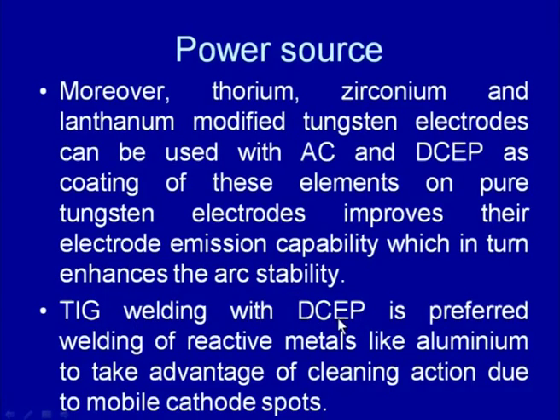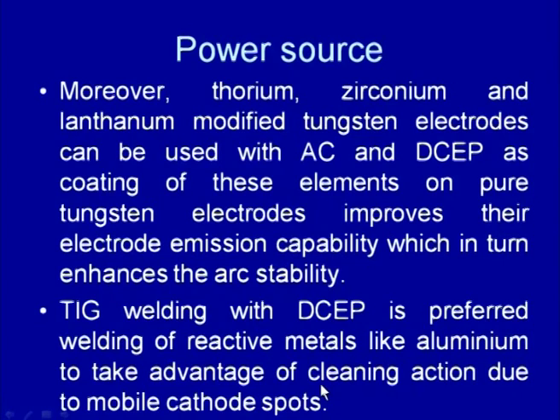In tungsten electrode welding, DC EP is preferred for reactive metals like aluminium, magnesium, stainless steel, etcetera, to take advantage of the cleaning action. We know that when the electrode is made positive, the workpiece acts as a cathode, and with these metal systems, a very mobile kind of cathode spot is formed, which helps in cleaning action, because the mobile cathode spot helps to loosen the oxide layer which is formed during the welding on the base material, and that loosening leads to easy removal of the oxide layer from the base material. That's how the use of DC EP helps in cleaning action during the welding due to the mobile cathode spot formation.